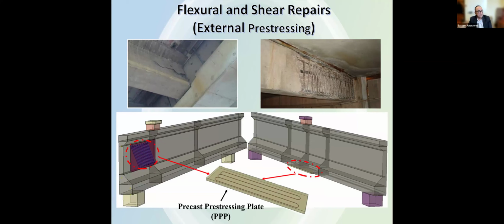It's called precast pre-stressing plate, the PPP concept, where we basically have a precast plate fabricated somewhere else and having a coil, if you will, of SMA that's pre-strained, not activated yet. You place it in that plate. You ship it to the site, you mount or attach it to the surface of the concrete where it's needed for repair or strengthening. For example, here it could be a web or it could be a flange. It could be a very tight region because really you don't need any anchorage block or system. Once it's ready, you apply the pre-stressing force by simply heating the wire inside the plate. The pre-stress transfers to the substrate or the surface underneath.